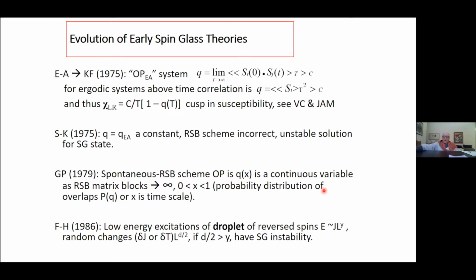And one of the ways is you look at the probability distribution of overlaps. You use the order parameter and you look at what that gives you. Is it significantly strong enough to give overlap with other order? How do these local order parameters differ? There have been numerous attempts from the theory side to do timescales. As we tried to do timescale measurements, the experiments are coming out recently of somebody waiting 2 or 3 weeks at a constant temperature.